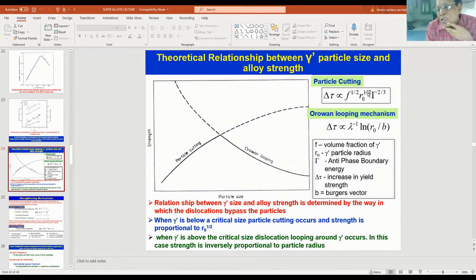When the particle is cut, gamma prime is an ordered phase. It is cut, and it will form an antiphase boundary, and that will give very high strength. When the looping mechanism is operating at high particle sizes, the particle size and spacing are inversely proportional. Here it is directly proportional, and there it is inversely proportional.